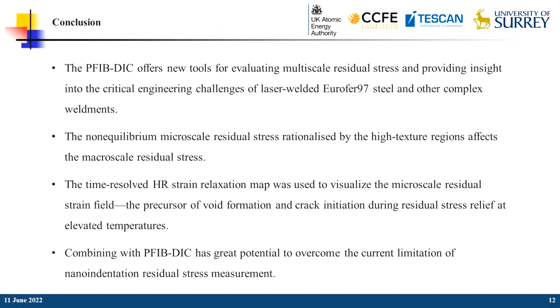The residual stress contributes around 25% to the hardening and softening in the fusion zone and the heat-affected zone. Our method can also be applied for many other similar metal joints, for example the in-vessel fusion components and even more complex material systems.